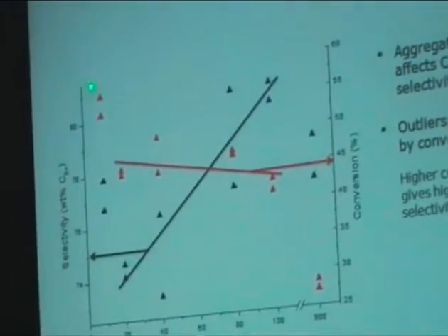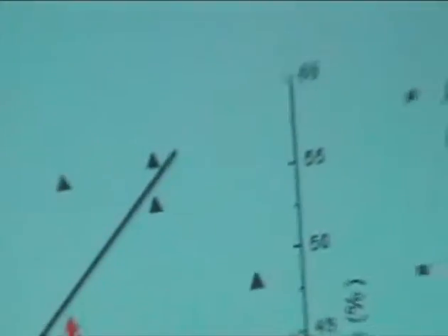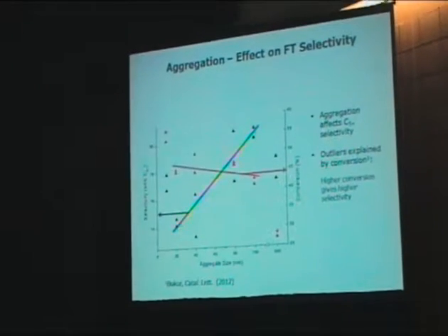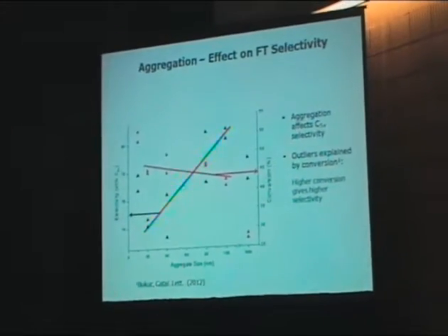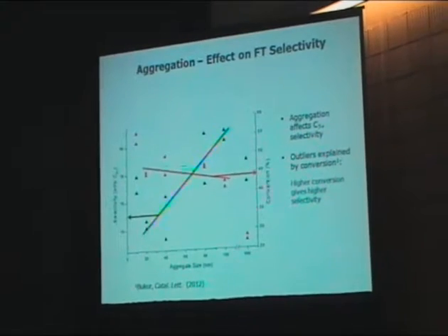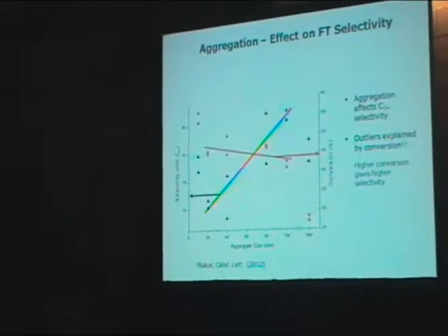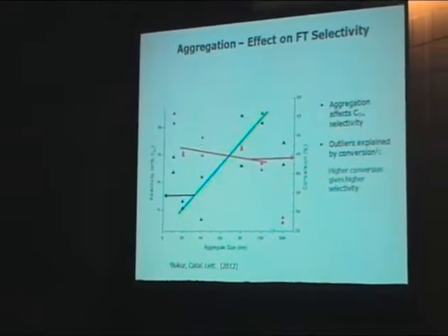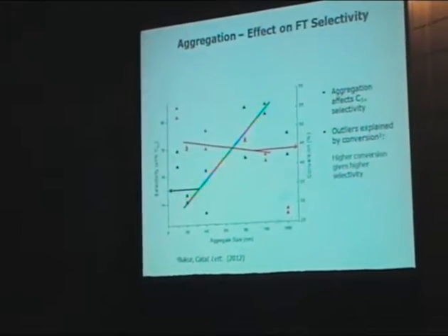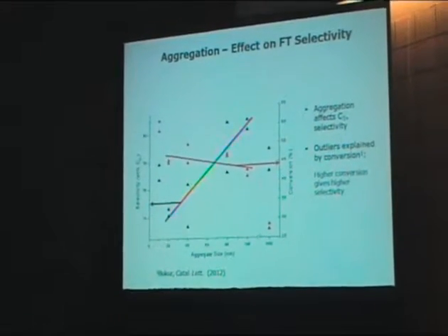Of course, in FT, C5 plus selectivity is key. We don't want the methane, often we don't want the C2 to C4. We prefer the liquid products, and the liquid products are C5 plus. So this is C5 plus selectivity from 72 to 82%, plotted here as a function of this aggregate size. And there seems to be a rough correlation with aggregate size, although some people may say a horizontal line will do as well. But the points that deviate are either because of very high conversion in this case, or low conversion because of the lower activity of the large aggregates.